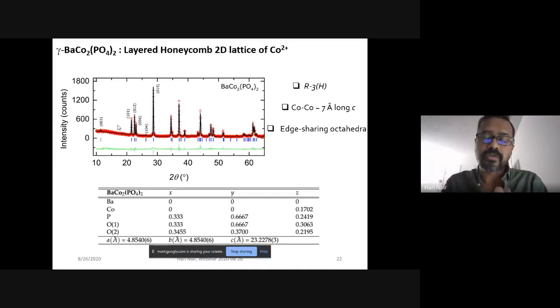Now, we also found out from this that the separation between cobalt and cobalt along the C axis is about 7 angstrom, which is good because it already imparts some sort of two-dimensionality to the layers of cobalt. So I'll have to agree that if you say it's not two-dimensional because it's already a crystal, that is true. We are looking only at the cobalt layers, which are 7 angstrom separated. So it is not essentially very accurate as two-dimensional, but I would say it is quasi two-dimensional.